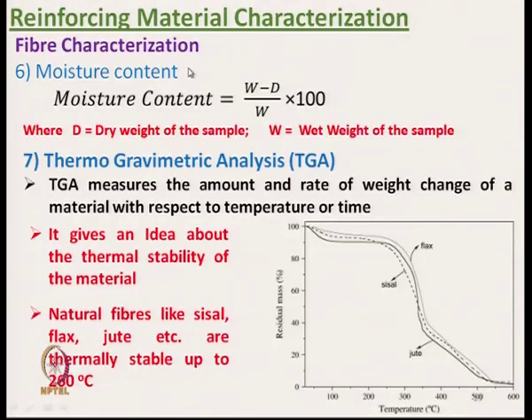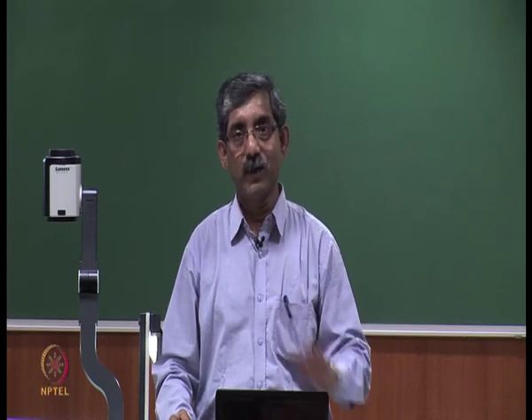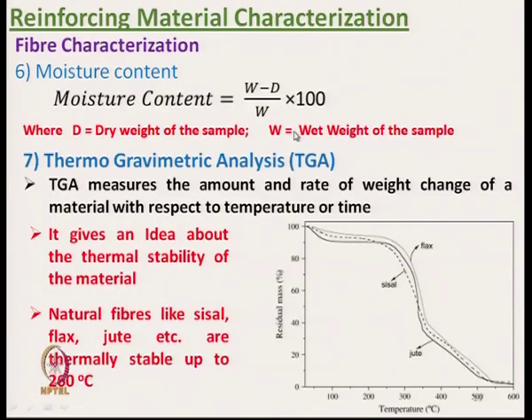And another characteristic of reinforcing material is moisture content. So, moisture content we can measure by measuring the dry weight of the sample and wet weight of the sample. So, we take the material and we first condition the material at standard temperature and humidity, and after that we take W, which is the wet weight of the material, and then we dry the material, it is a bone drying, which removes all the moisture present in the structure, and we get dry weight D. W minus D by W multiplied by 100, we can get the moisture content of the material.